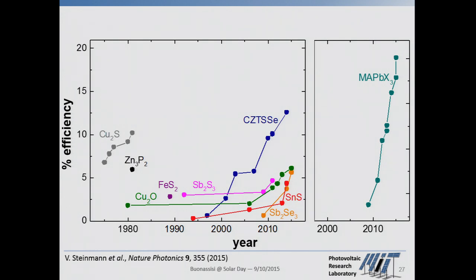And the really exciting thing about this is the efficiency skyrocketed from 2008 to current day, from around 2% to over 20%, unstabilized. But it's a very high efficiency nonetheless. And this material is very promising in that it's low capex, but it's also unstable and tends to degrade within hundreds or thousands of hours, and by degradation on the order of 10%.